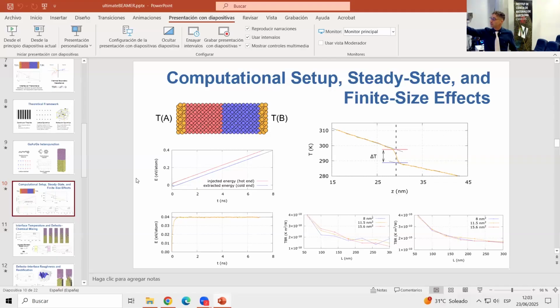And in order to achieve convergence, you need your system to reach the steady state pretty quickly. In order to do this, we increase the temperature difference, because everyone has a pretty fair physical intuition of this. If I apply 1 Kelvin of temperature bias, it will take minutes, probably hours, to get to a steady state. So it's completely impossible to perform the simulation. It would have taken more than my whole PhD to perform just one data point. So we use these incredibly high temperature gradients, which are way higher than the temperature gradient from the core of the sun to its surface.